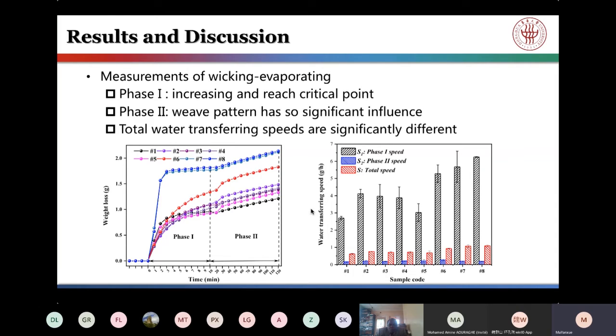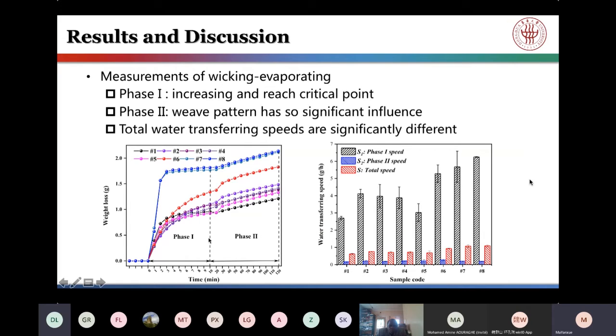According to a statistical analysis, the moisture transfer speeds of the 8 samples were significantly different in phase 1. It can be observed from the figure that their overall behavior followed the same trend. Each of the 8 samples reached their crucial points in phase 1. And the water transfer speed finally had a dynamic balanced value after achieving the longest wicking distance.